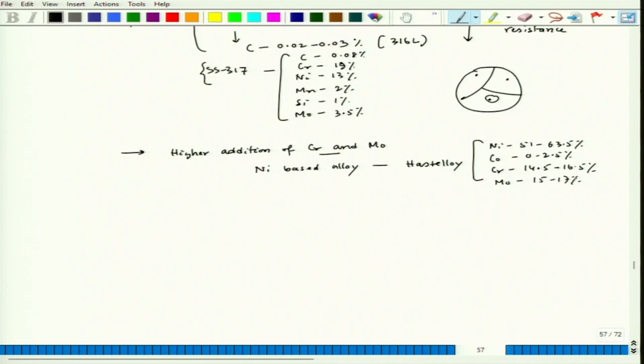So the extremely high level of molybdenum actually gives an excellent pitting resistance, and we have a little bit of iron, tungsten, and a little bit of manganese, 0 to 1%. So this is a typical composition of Hastelloy.